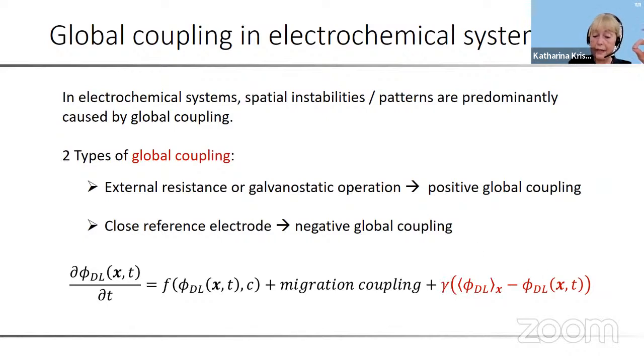And a negative global coupling means you have a negative gamma, a negative coupling strength, which means the total term is positive, and your perturbation to larger values of the electrode potential will be enhanced. Only at this position, where the electrode potential is already a little bit larger than the average, it will be pushed to even larger values. And if it was a little bit smaller through a fluctuation, it is pushed to even smaller values.